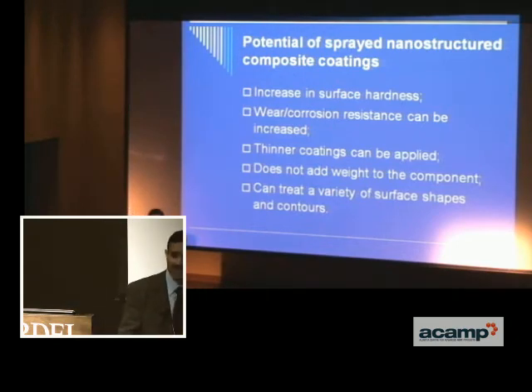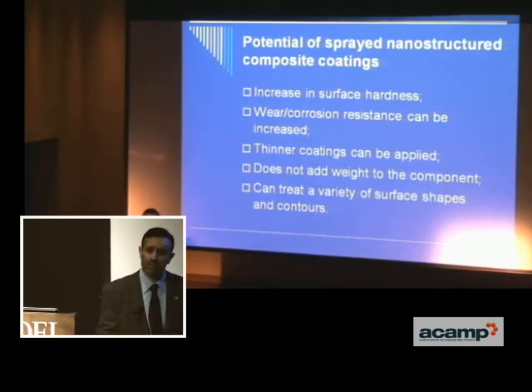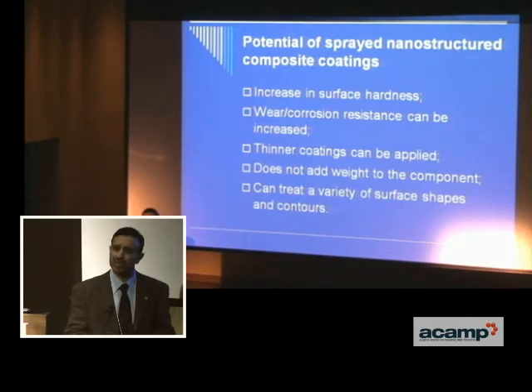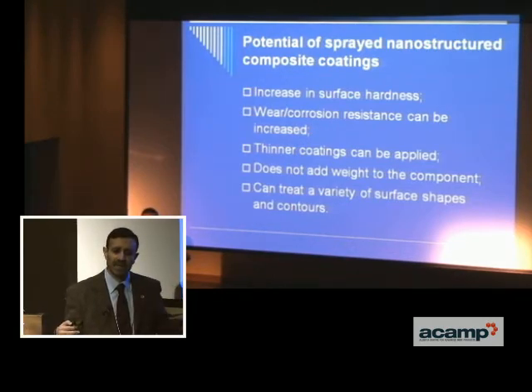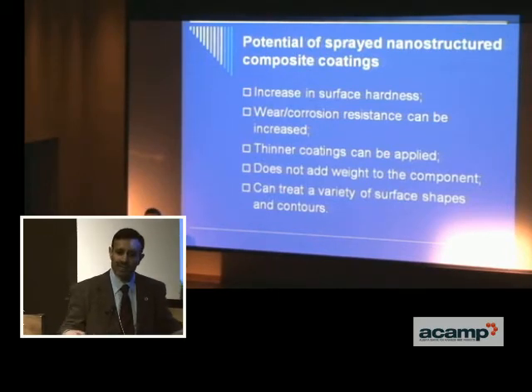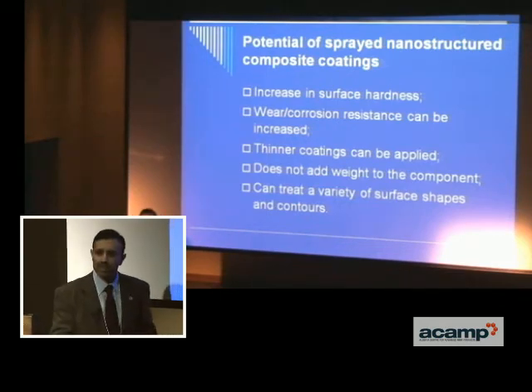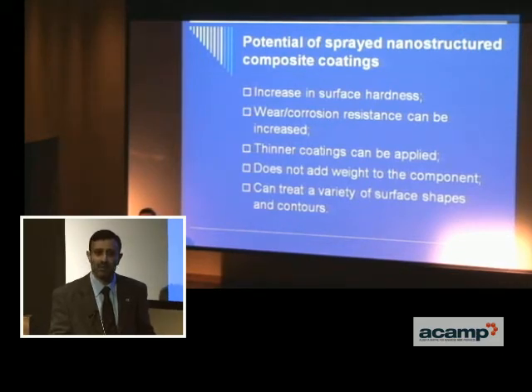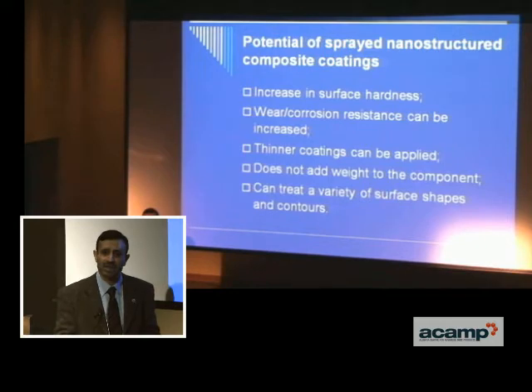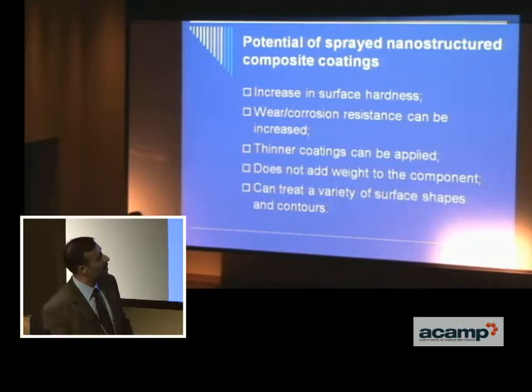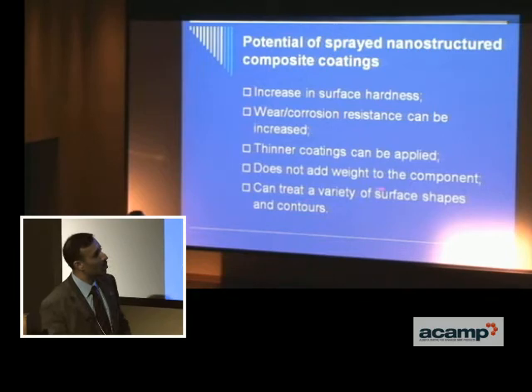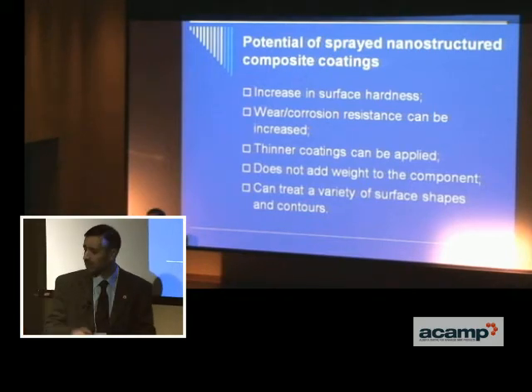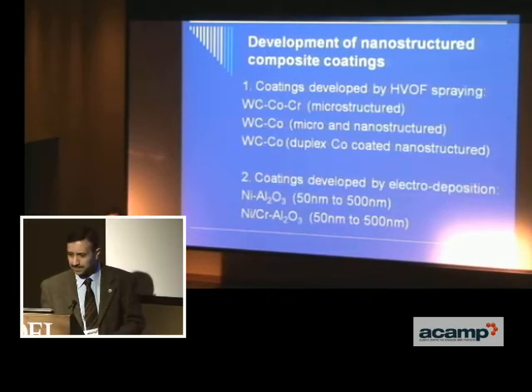One of the things that we want to get away from is that the industry currently uses simple heat-treated materials. In other words, taking thick sheets or plate material that has been heat-treated and welded into place to prevent degradation. So by using much thinner coatings which have wear resistance equivalent to, or if not better than, what we're doing at the moment, we can substantially increase efficiency in that way. The other thing is that we can also treat all kinds of shapes and sizes as well. So contours are an important thing as well.